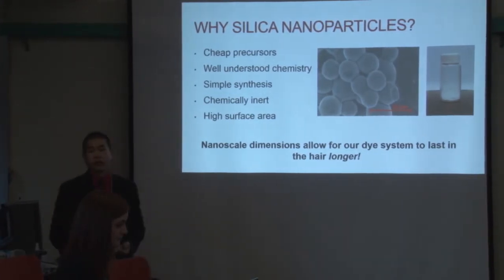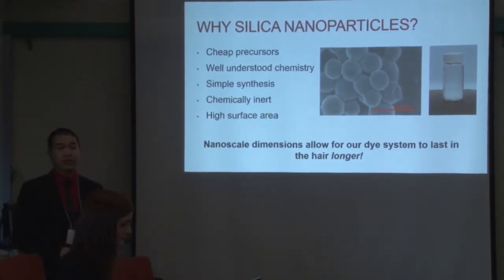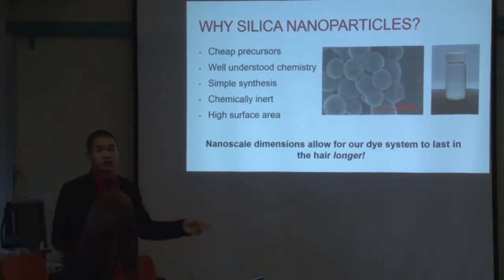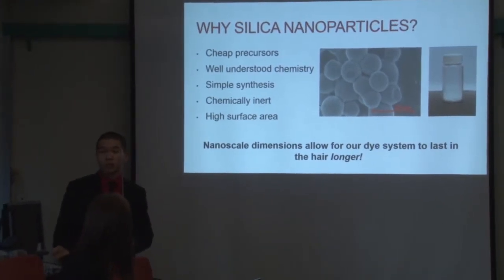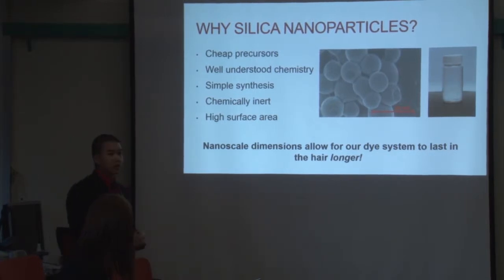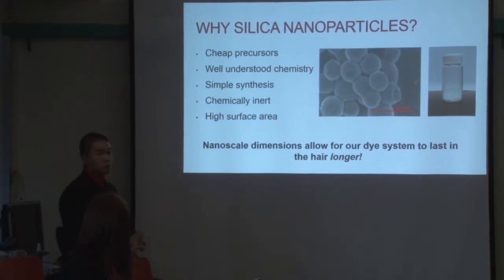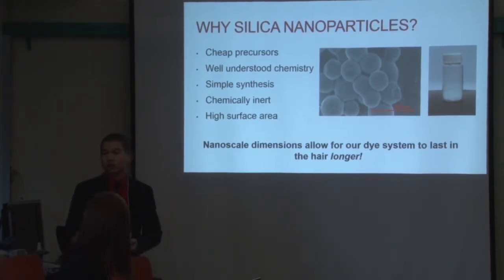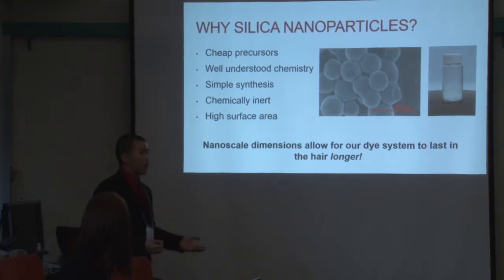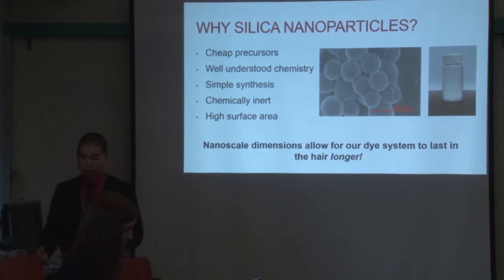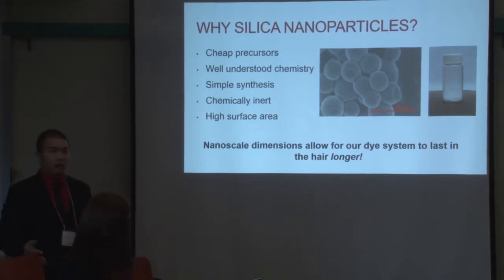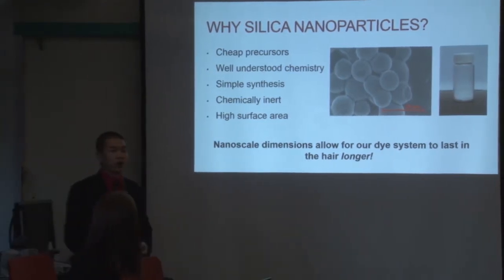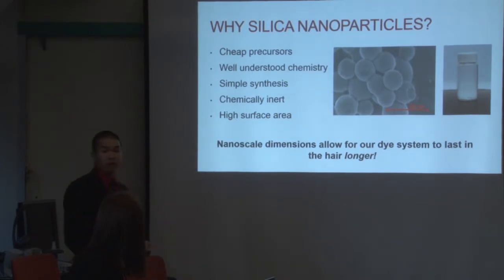So why did we choose silica nanoparticles? Well, for one, silica is very cheap and easy to synthesize. In fact, our process only takes 2 steps, so it's a modification of the Stober process, and it doesn't require any expensive or exotic chemicals to produce. 2, silica has a very well understood chemistry. Its properties are very well defined since it's been around for a very long time, which means that any parameters that we change will give a very predictable result. So we can tune the morphology of our silica particles to suit our needs very easily.